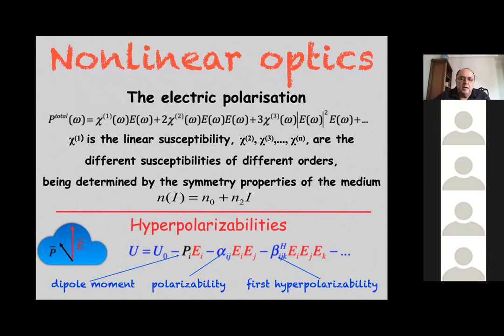On the other hand, if you take into account just the absorbers inside the particles, which we can name molecules, although it's not a molecule, Fe3O4 for example, in the crystal, we can have the polarization and the electric field. If there is an angle between them, the energy of this coupling has a linear term, but if this electric field is high enough, you have more terms which are important to define the energy of this dipole in the presence of the electric field.